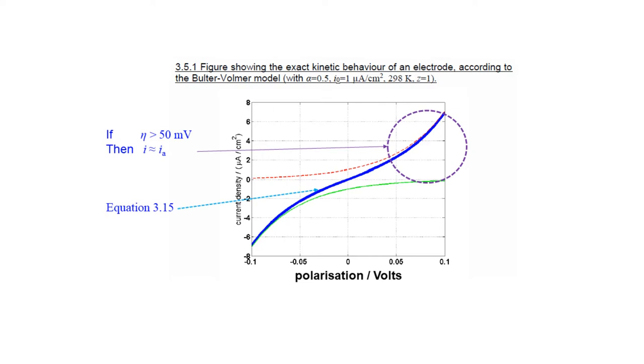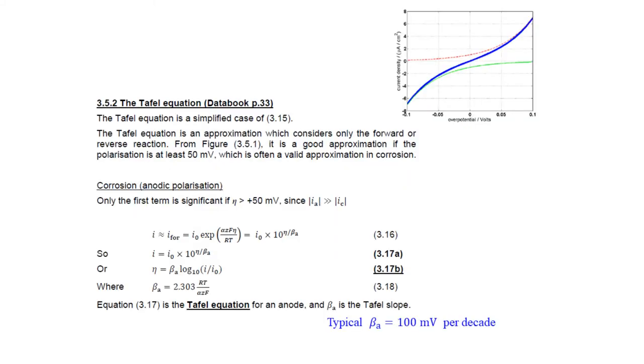Likewise, for moderately large negative polarizations, more negative than minus 50 millivolts, the forward process minus the backward process is dominated by the much stronger backward process, just the negative exponential. And in that case, we only take the backward exponential term, and this gives us, again, an equally good approximation of the total equation. So this is very good, because it means we can produce, in section 3.5.2, the Tafel equation. Our Tafel equation is not going to be a good description of electrodes which are very close to their equilibrium potential, but since in reality most interesting electrode reactions are at least 50 millivolts away from their equilibrium potential, we can use this approximation, and we'll just take the relevant forward or reverse process.